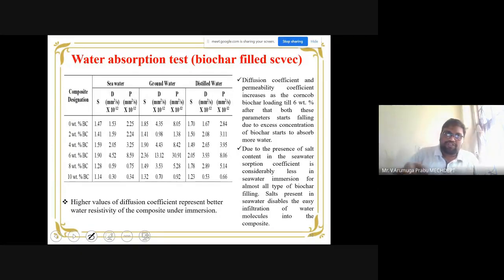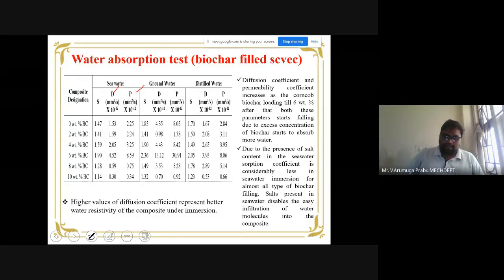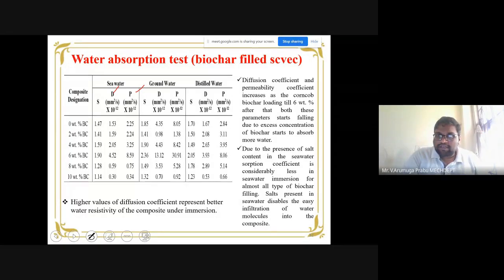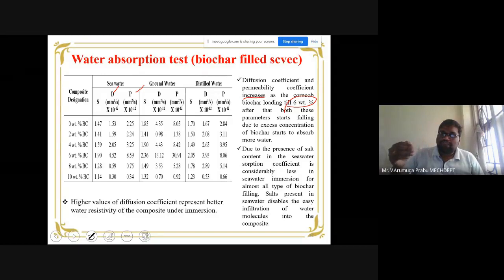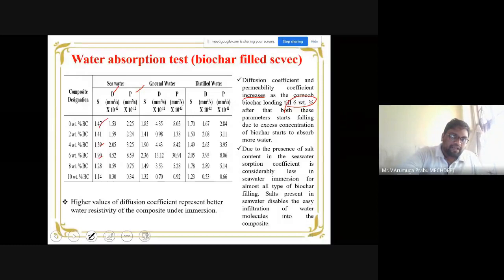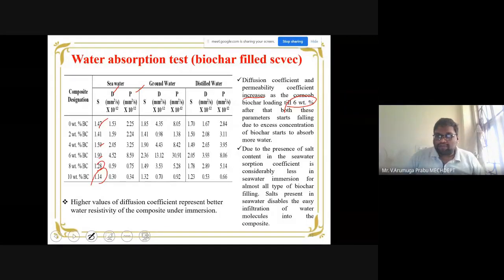How am I ensuring this? If you see the table, D is the diffusion coefficient, P is the permeability value. The formulas for these two are available, and many researchers have already used them. So we follow those, and we find the moisture absorption resistance. By means of D and P values, we are able to notice how the composite behaves toward moisture resistance. Here the coefficient is going to increase up to the 6 weight percentage case. So from 2 to 6, the values are on an increasing trend. If you notice the table, after that there is a decline. See, 1.9, then it starts declining from 8 to 10 percentage.